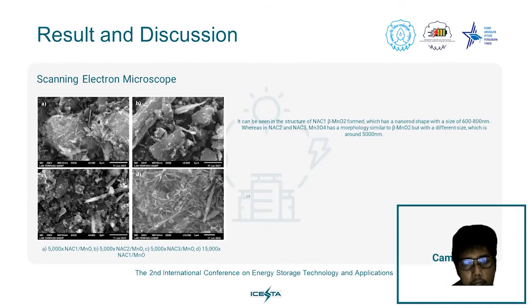And then we test it with scanning electron microscope. For the scanning electron microscope, we magnify it at 5,000 and then 15,000. At 5,000, it can be seen in the structure of NaC1 that beta MnO2 forms a nanorod shape with a size of 600 to 800 nanometer. Whereas in NaC2 and NaC3 here, Mn3O4 has a morphology similar to beta MnO2 but with a different size.